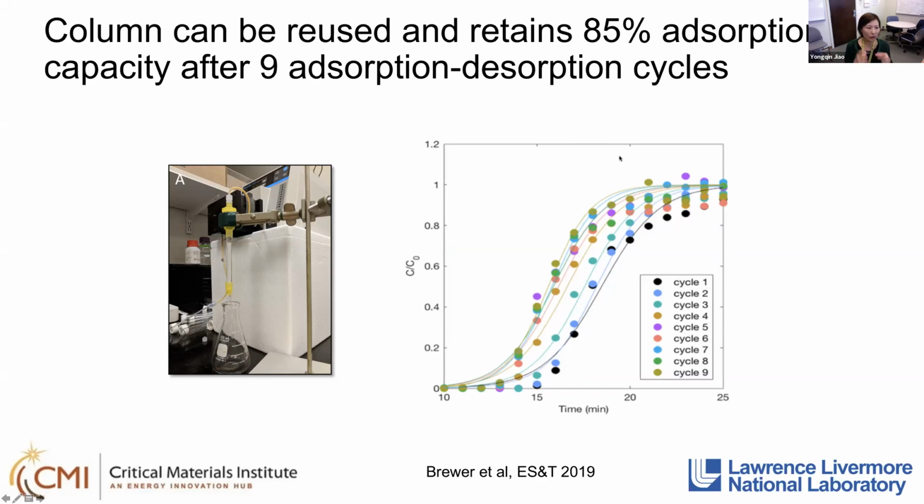And from my literature reading, those are less specific. They bind metals less specifically than the biological peptide or protein ligands that we're looking at. Also, similarly to other surfactant utilization, if we were to apply it to an extraction scheme, you would use a lot of solvents for the binding and flotation separation to occur. So the biosurfactant case for bioflotation is another pathway of using biological ligands for rare earth or metal recovery or bioremediation, and is in parallel with what we're working on for the adsorption desorption approach.